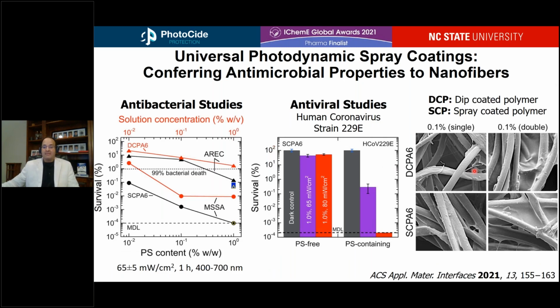And so when we take these materials, whether they're dip coated or spray coated, and we do some antibacterial studies to determine their efficacy, as you can see here on the left-hand panel, against methicillin susceptible Staphylococcus aureus or against antibiotic resistant E. coli, again, gram-positive and gram-negative pathogens respectively, we have fairly good inactivation to our minimum detection limit, 100% inactivation of the Staphylococcus aureus, and 3 log units, 99.9% inactivation of our antibiotic resistant E. coli. Again, the y-axis here for these panels is always going to be shown in a logarithmic scale.